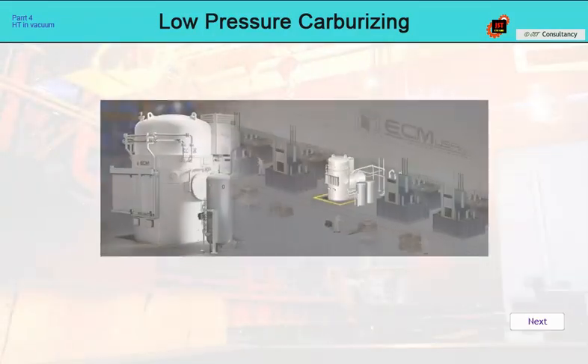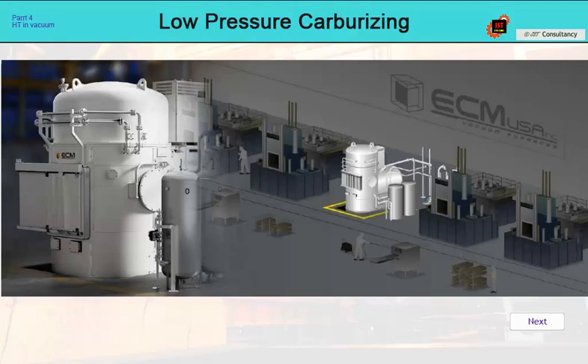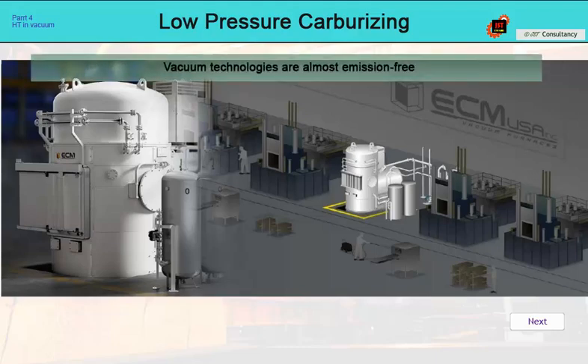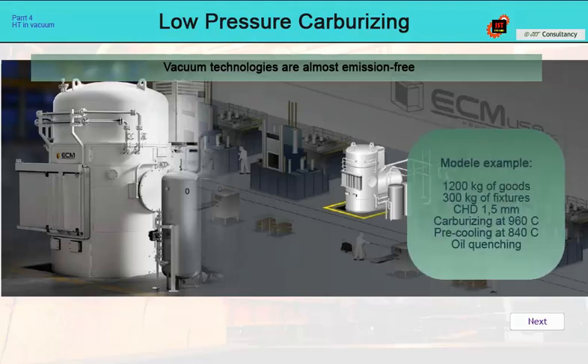When deciding to purchase low-pressure carburizing equipment, it is important to look at it from the perspective of energy consumption and impact on the carbon footprint. The LPC technology itself is emission-free, as are other vacuum technologies. For comparison, we can give an example of a load of 1,200 kilograms of goods plus 300 kilograms of fixtures, carburized to CHD 1.5 millimeters, processed in an ECM Eco 1299 furnace with oil quenching.